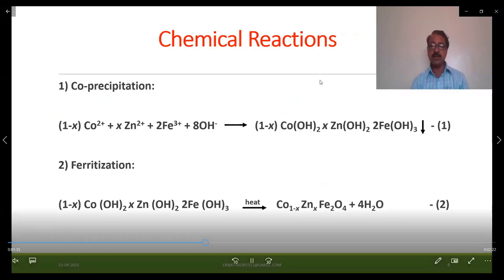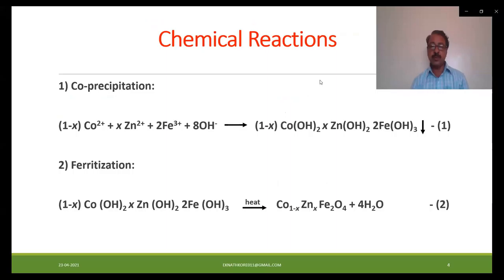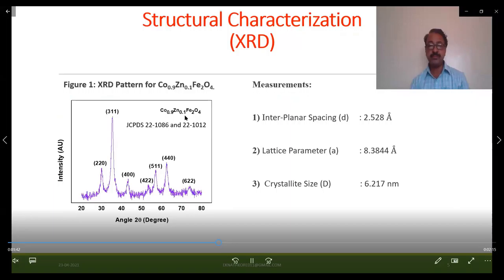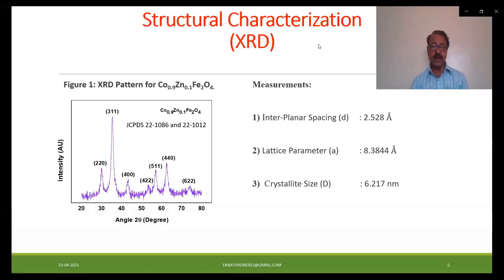The chemical reactions which took place show two distinct steps, co-precipitation and ferritization. The as-prepared samples were characterized by XRD and FTIR for structural characterization. The characteristic peaks in XRD match with JCPDS card numbers 22-1086 and 22-1012, which confirms the formation of spinel structure of the ferrite. These are interplanar spacing, lattice parameters, and crystallite size of the sample.